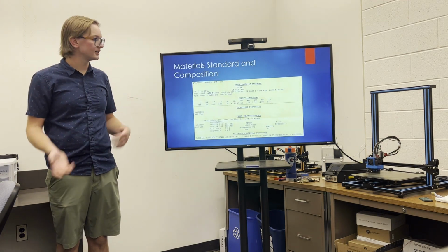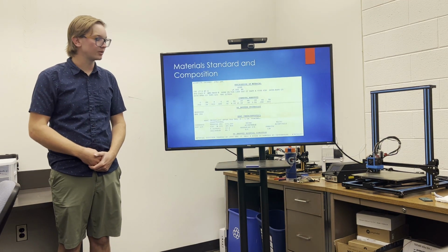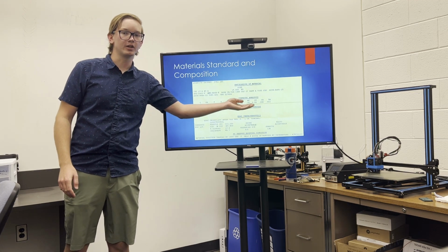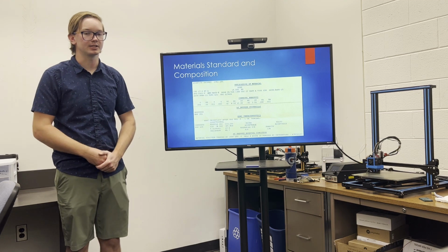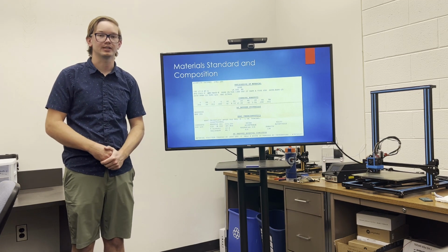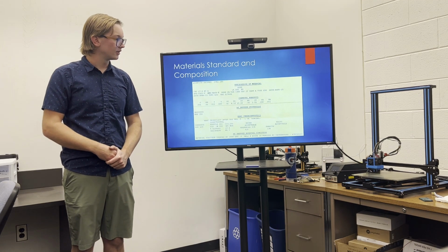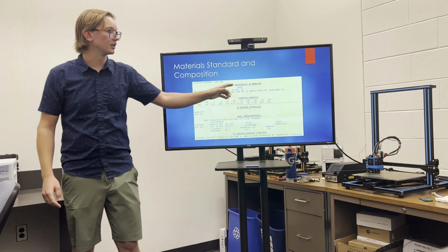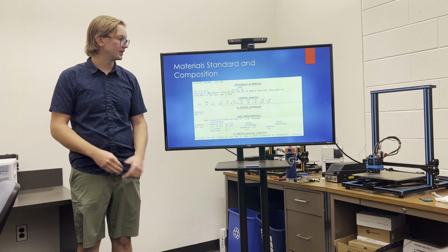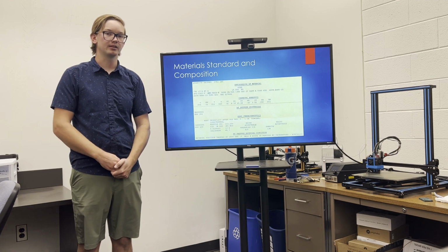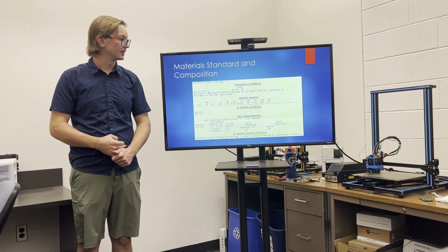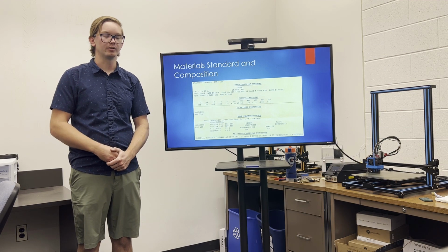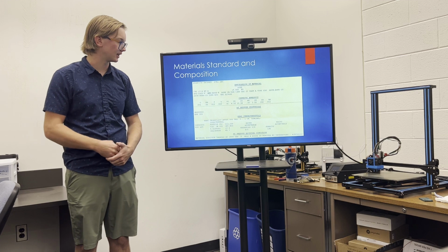So, this is the manufacturer's sheet that was provided with the billet. We can see that the chemical composition of the billet falls entirely within the ASTM standard for this type of steel, which is referred to as type 630 by ASTM. The only difference is the sheet calls out columbium and tantalum. Columbium is an old name for niobium, and it uses a combination of columbium and tantalum to meet the standard's niobium requirement. This is acceptable as per a footnote under the 2019 version of the standard.